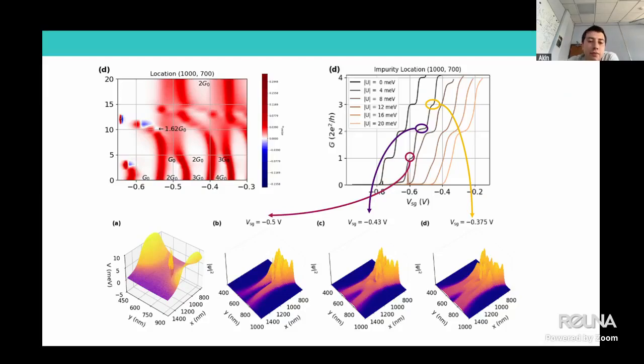And in only two-dimensional experimental data, one may see a plateau-like structure, but that could be coming from multiple modes being in the system. And here you can see the second mode being affected by two modes in the system and a third mode trying to enter, and then the third plateau actually has 4 partially transmitting modes in the system.